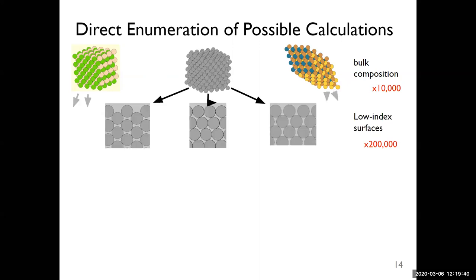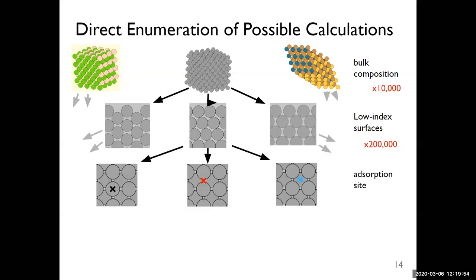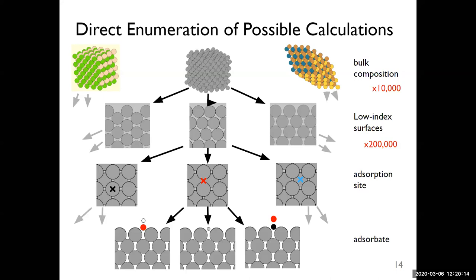And if I consider different low index facets, a lot of these intermetallics are missing most of the symmetry that we think about in solid single component metals. We have about 200,000 different surfaces. So that's already up by about a factor of 20. If we then think about how to place a molecule on a surface, we can do some math in order to figure out what are the interesting symmetry reduced sites. And again, people in Materials Project, PyMatGen does an awesome job of this. There are some other similar packages. When we get to that level, we end up with about 15 million different sites that we can consider from the space.